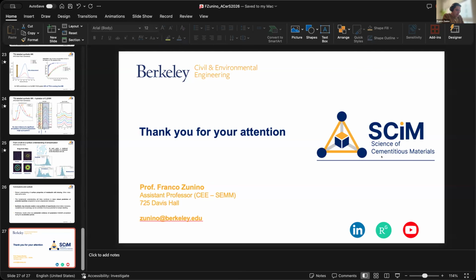And at the end of the day, I strongly believe that it's going to be a portfolio of SCMs that we are going to have available, and that each regional context is going to find some make more sense than the other. Of course, calcined clays offer a reactivity that most natural pozzolans cannot achieve. And therefore, for special applications, it might even make sense to move calcined clay from one place to the other in order to produce this high performance cement. But for lower demand applications, I think that there is no reason why we cannot exploit local deposits of materials in order to decarbonize cement.